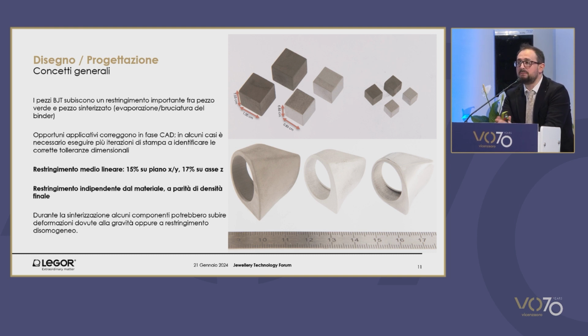So the size monitoring in terms of size prior and after sintering in steel, platinum, and silver is an independent value, at least if we consider powders that have been atomized in inert gas. This is the ideal case, so once you decide the size, I can proceed with the production. But on top of that, you have to think about the possible softening of the piece and the presence of gravity, which plays a role also during sintering.